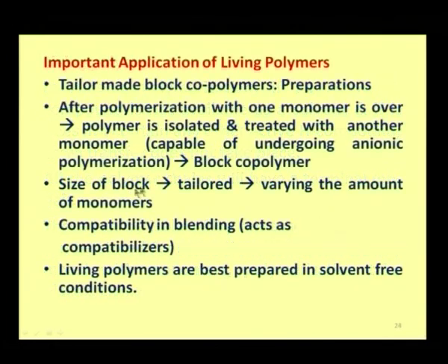What are the important applications of such living polymers? Basically, they are very useful in tailor making block copolymers, in the preparation of block copolymers. What happens is, after polymerization with one particular monomer is over, the polymer is isolated and then treated with another monomer molecule, which is capable of again undergoing anionic polymerization. This leads to what is called a block copolymer, which is a polymer where you have blocks of different monomers.